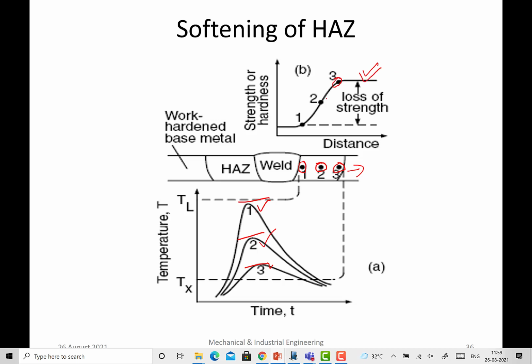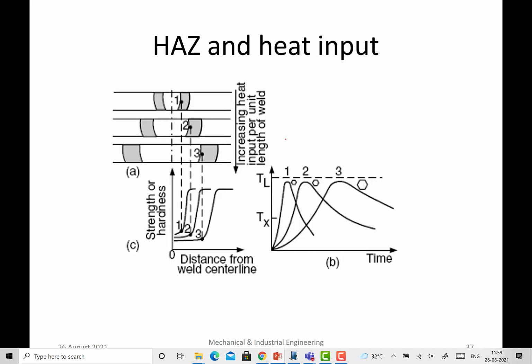So at 3, there is a marginal drop, there is a significant drop, and further drop at location 1. These you can attribute as a loss of dislocations or the loss of the precipitates, overaging, grain growth, all these. Okay. Now what happens when you apply a different amount of heat? Say, if you have applied a heat of 0.2 kilojoule per mm, 0.5 kilojoule per mm or 2 kilojoule per mm. There is a lot of difference in this.